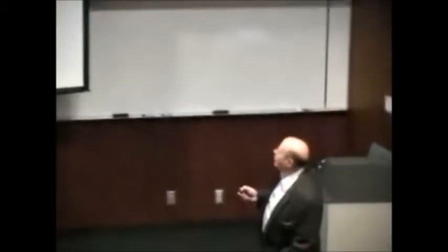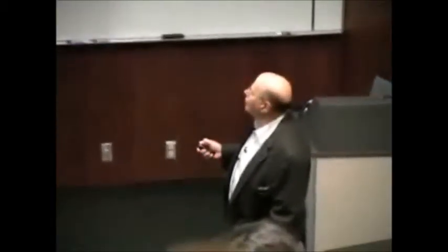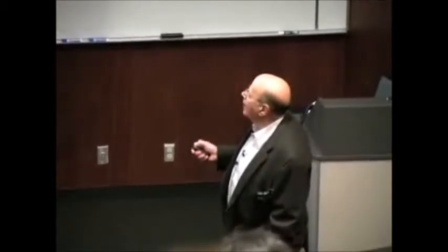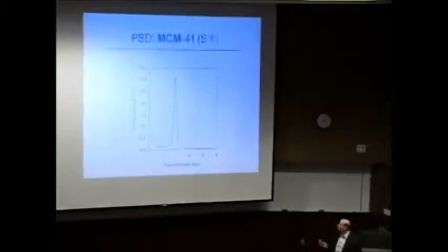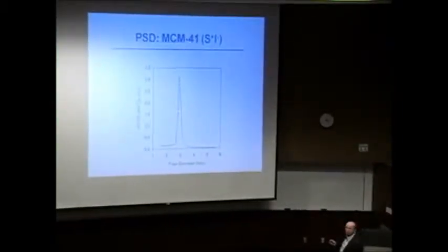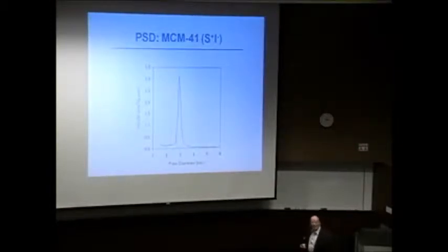But without going into those details of what model we're fitting here, you could see that the apparent average pore size is around 3 nanometers, and the width at half maximum here is of the order of 1/4 of a nanometer. So we're talking about a 30 angstrom pore plus or minus 2.5 angstroms. That's remarkable fidelity to the pore structure.